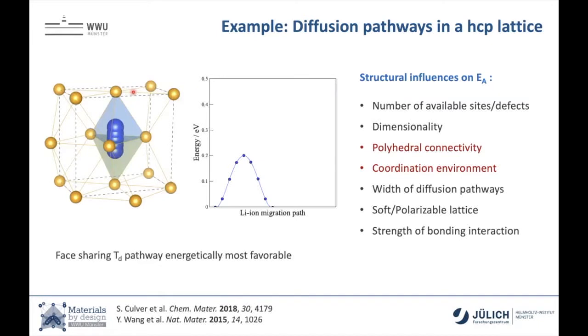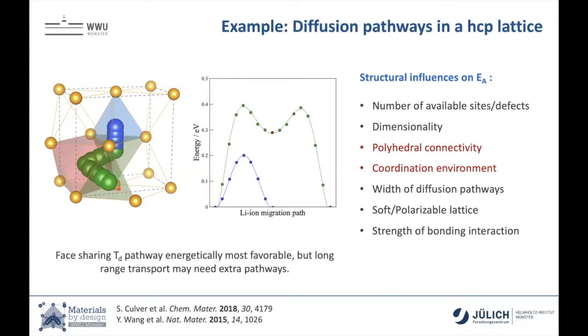Three-dimensional conductors are better than one-dimensional conductors. We think about how the polyhedra of our mobile ion are well connected. Schematically, in an HCP lattice, an ion on a tetrahedral site wanting to jump to an adjacent tetrahedral site through a face-sharing arrangement doesn't cost a lot of energy — about 0.2 eV — because we change coordination from four to three to four, which is like breaking one bond and forming a new bond. But for long-range transport, we have to go through an octahedron to the next tetrahedron, changing coordination from four to three to six. Lithium might be unhappy in that higher-energy intermediate state, so the activation barrier is higher. This is how the polyhedral arrangement alone affects your energy landscape.